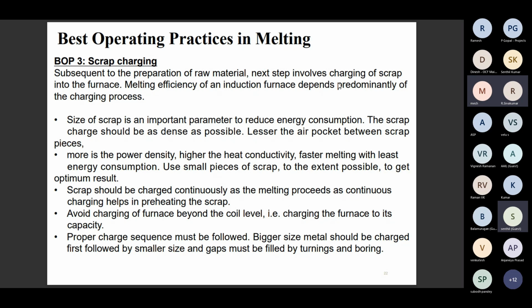consumption can be reduced. If any waste heat is produced inside the foundry, that waste heat can be used for preheating the scrap charge, so that the scrap temperature can be raised from room temperature up to 60 or 70 degrees. The energy consumption in the furnace is also reduced.